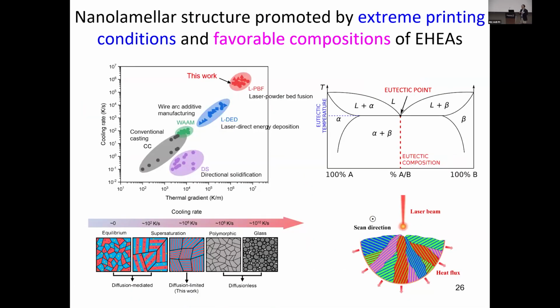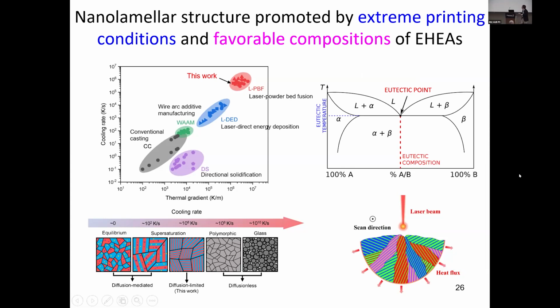So now we have dual phases, right? Different from the stainless steel I just showed, in that case we only have the chemical dislocation cell structure in a single FCC phase. But now we have a mixture of FCC and BCC nanolayers, and also the micron-scale colony structures. The extreme printing condition enabled a very high cooling rate and a large temperature gradient, and this really pushed the limit of the attainable microstructure length scale. So you can see we have a very small nanolayer thickness, while the eutectic composition facilitates the formation of this alternating dual-phase microstructure.